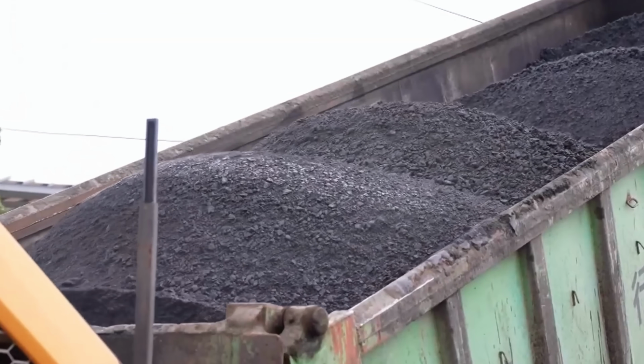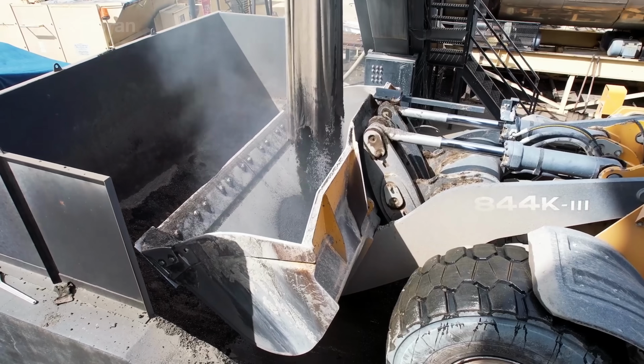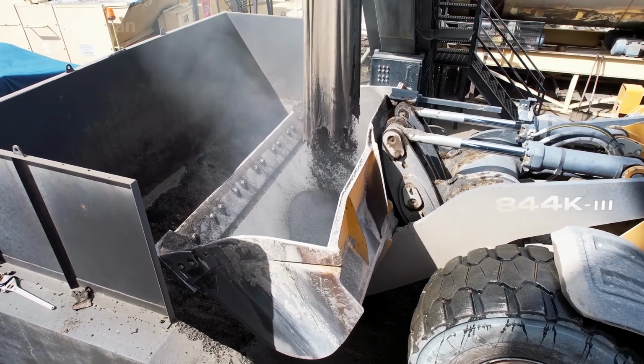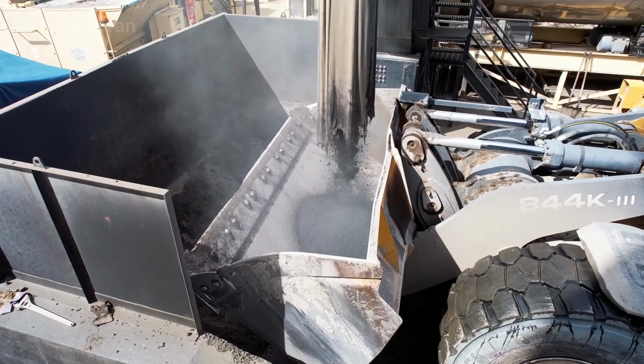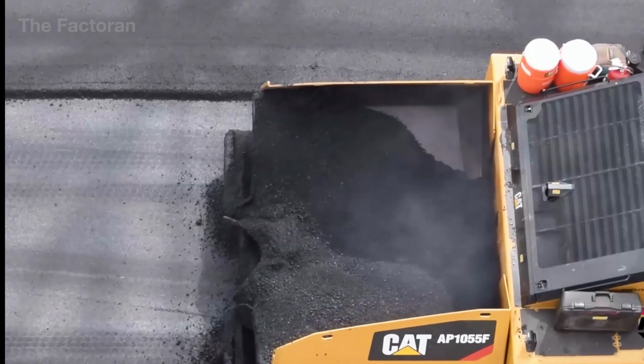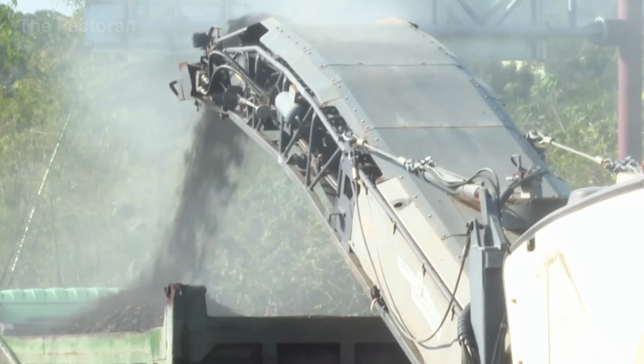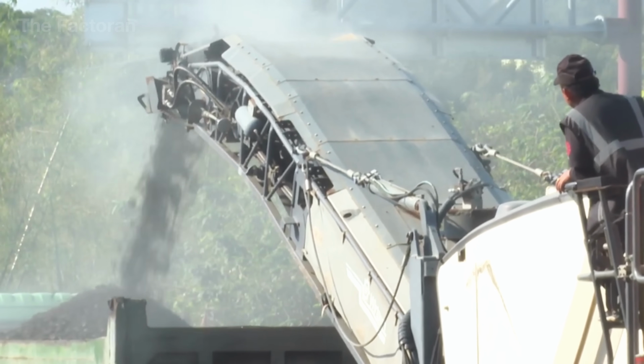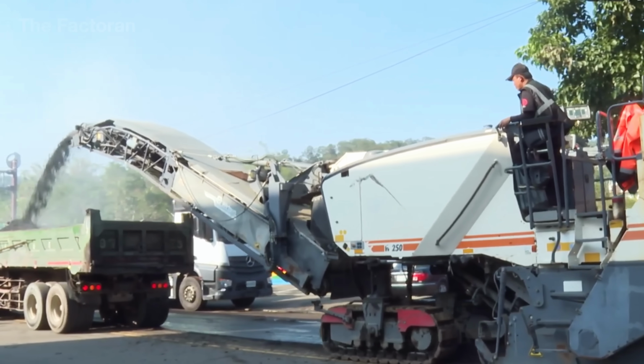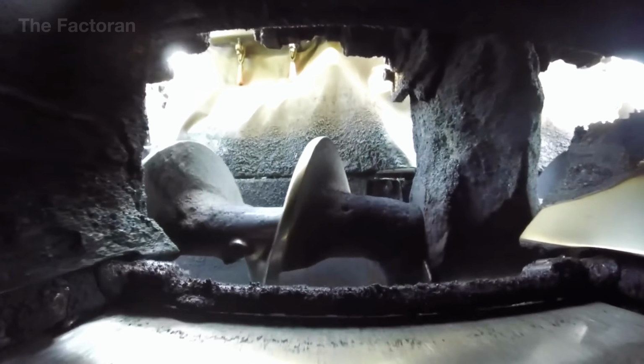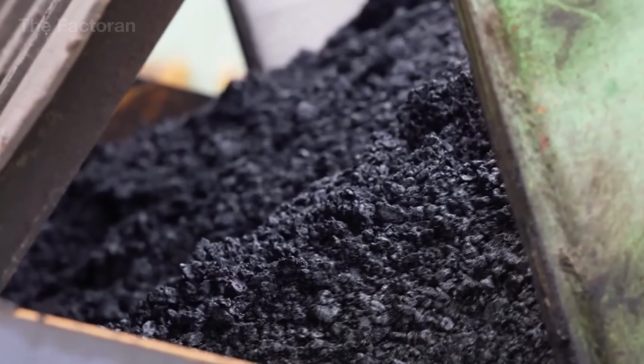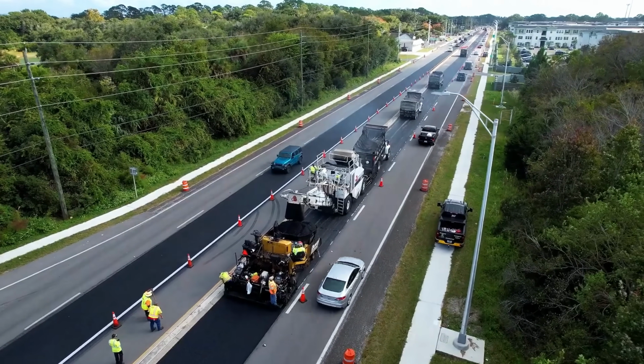As soon as the dump truck leaves the plant, the hot asphalt mix must be kept at the proper temperature throughout the journey. At the construction site, the truck reverses directly into the asphalt paver and unloads the mix into its receiving hopper. From there, conveyors and augers distribute the material to the rear, laying it down as a continuous layer across the prepared roadbed. At the back, the screed, controlled by hydraulics and guided by laser sensors, ensures the mat is laid with the exact thickness, smoothness, and slope required by design. While the asphalt is still hot, a fleet of heavy rollers immediately takes position.